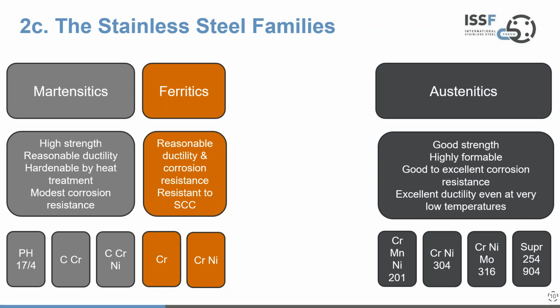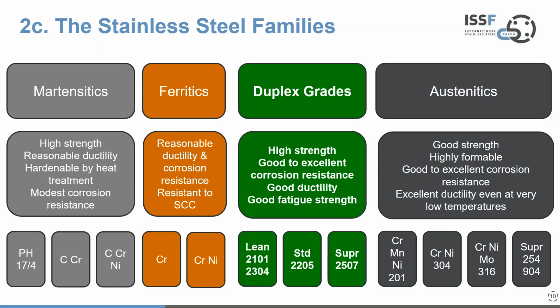Then we have the molybdenum enhanced grades like 316, which are often used in more aggressive corrosion environments. And then the highly alloyed family, or the super austenitic grades, which can be used in high temperature, very aggressive corrosion resistant needs environments.